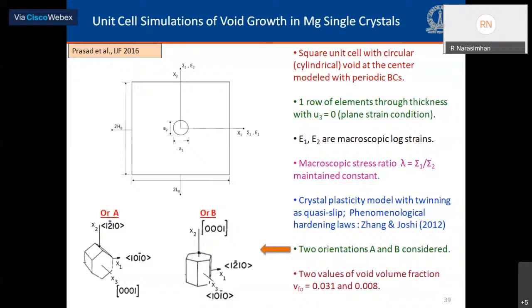So from the context of texture engineering, it would be better to look at single crystals. So that's the reason why we work with single crystals. We do single crystal simulations. So these are plane strain simulations with a square unit cell with a circular cylindrical void placed at the center of the cell, subjected to different macroscopic stress ratios, sigma 1 by sigma 2.